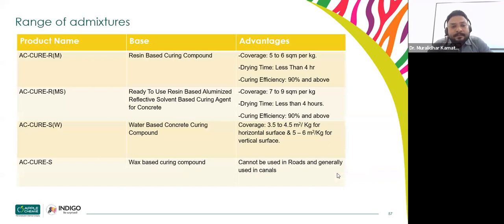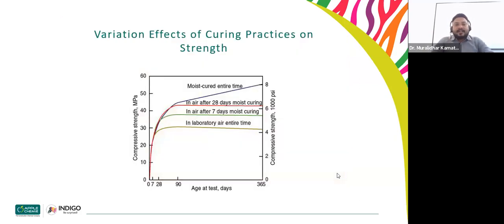These are the curing compounds: resin based, then aluminized reflective, water based, wax based. Generally wax based is used for roads and canals, your irrigation projects where canals are there. And for coverage and so on, we generally check the curing efficiency, and drying time should be less than 4 hours. If you look at the various effects of curing practice on strength, you can see in the laboratory that air curing gives less strength. After 7 days of moist curing, the strength is comparatively 4-5 MPa more.